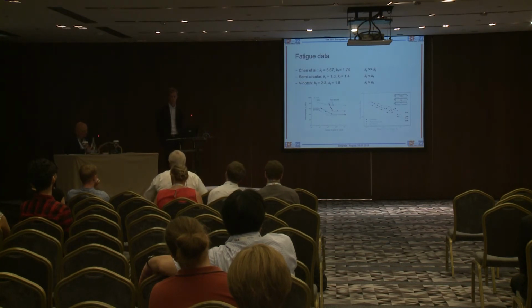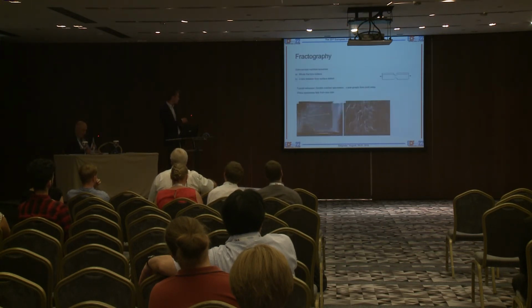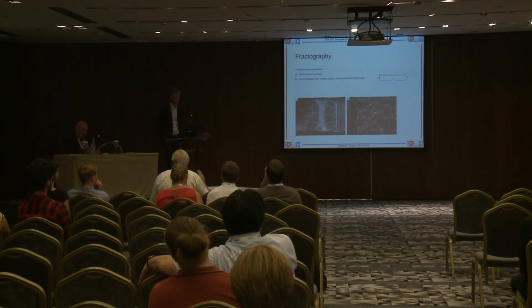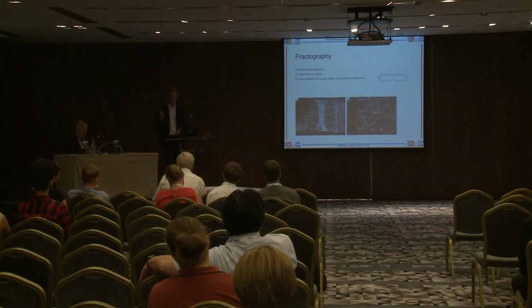As you mentioned, it's weird to see that the KF factor is higher than the stress concentration factor. Do you have any clue how that comes? Because all the literature, starting from Neuber in the 50s to today, says that the KF might just reach the stress concentration level. So when we evaluated this, we used the nominal geometry, as we see in the figure. But for additive manufacturing, we're not machining this to be a perfect surface. So the lack of fusion defect will, for example, act as a crack, and you would have the stress intensity factor from this. So based on what you're able to measure, you will get a really high stress, or a stress intensity, rather than a stress concentration, because of the lack of fusion defects. Is it answering your question? Okay. Interesting. Thank you.